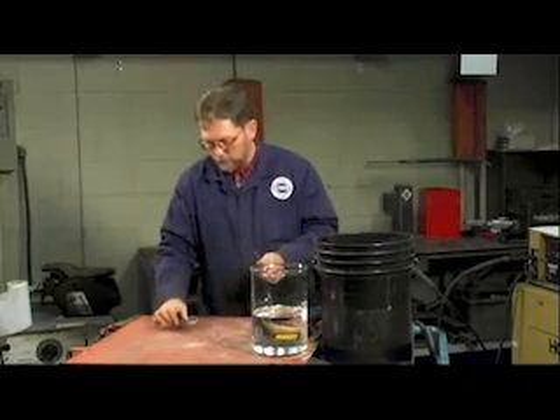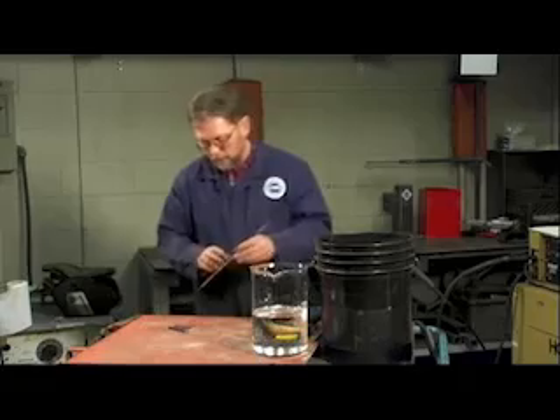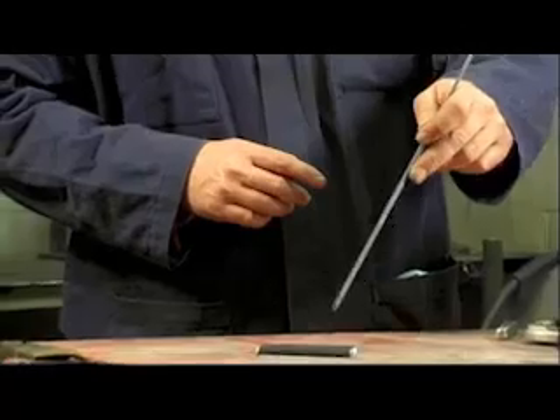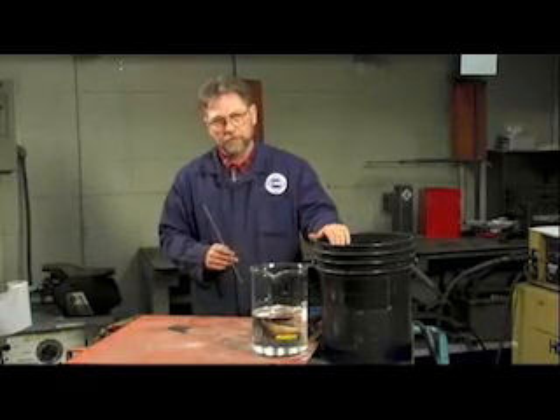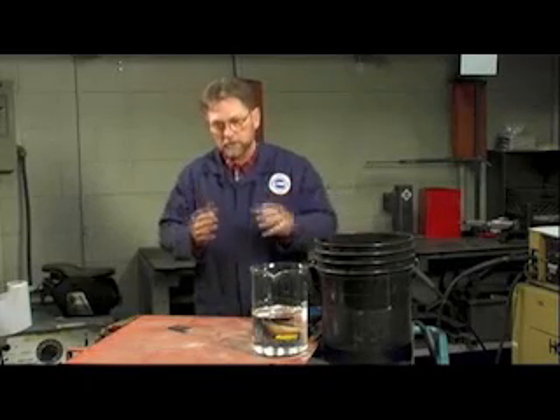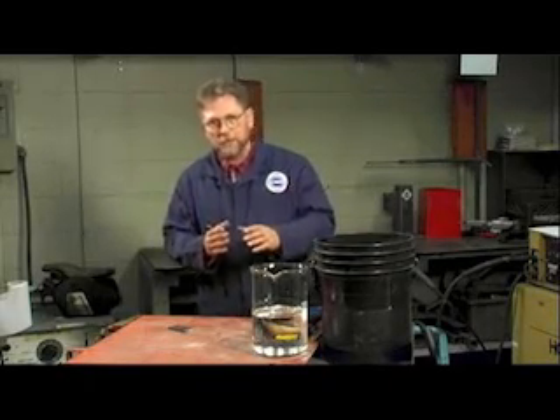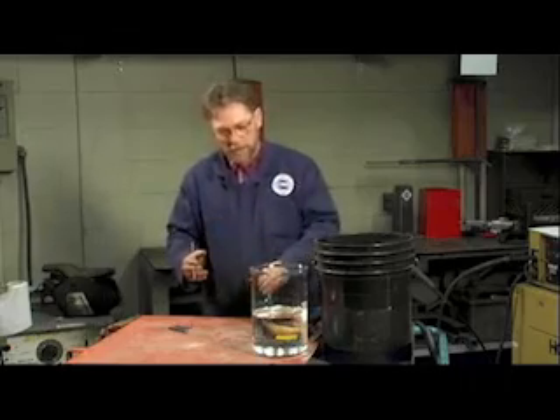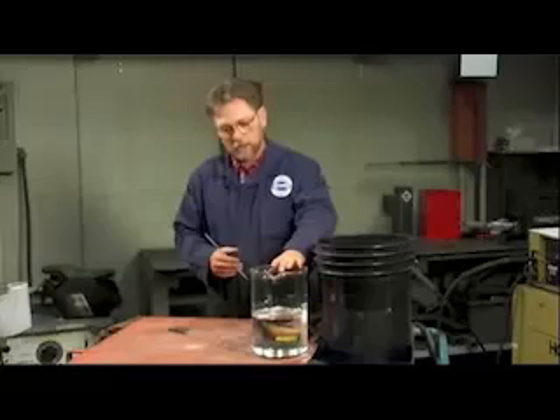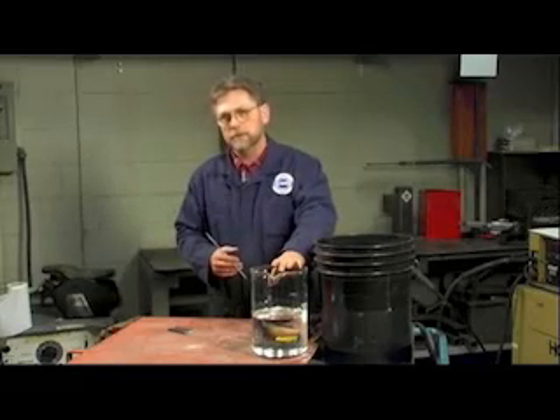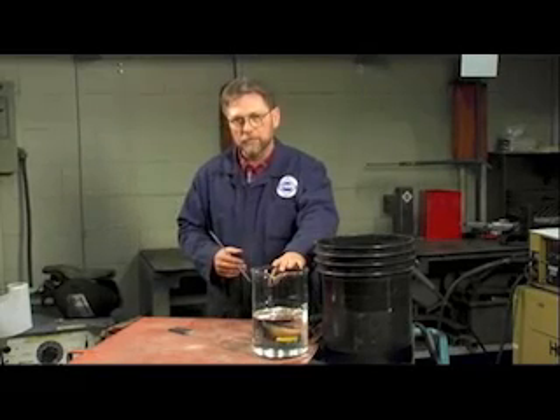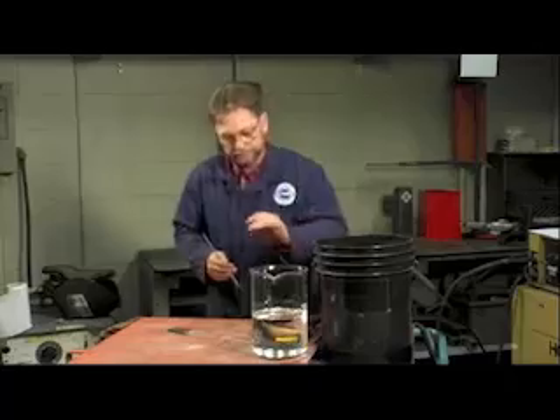So I'm going to make this weld with this rod. I'm going to quench this piece of material in the bucket of cold water. That's going to shrink the material down, trapping the gas in. Then I'm going to clean it off and dry it up, and put it in this beaker of mineral oil. This is just a clear light oil that will allow you to see the bubbles of hydrogen coming out of the weld at room temperature.